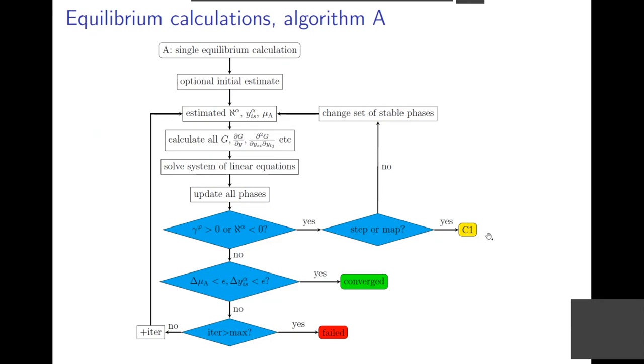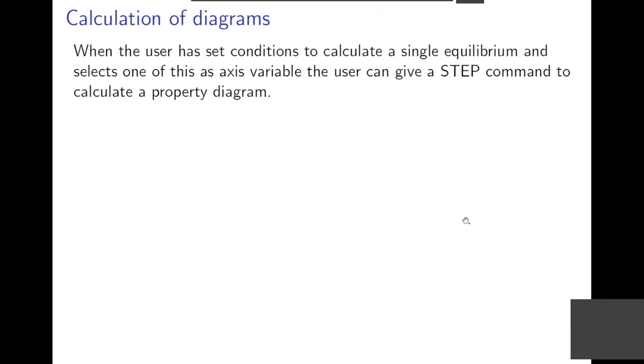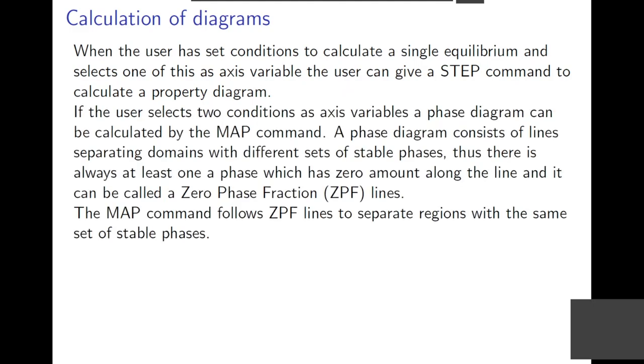If you have a step or map calculation, one goes to a second algorithm here. And there are basically two diagrams you make. One is the phase diagram and one is what we call the property diagram. In the property diagram, you have just one axis and you calculate how the system varies along that axis. The command in OpenCalphad to do a property diagram is a step calculation, and if you want to do a phase diagram, you do a map calculation. And the typical feature of a phase diagram is that it consists of lines separating domains with different sets of stable phases. So there is at least one phase which has zero amount along each line in the phase diagram. John Morral called them zero phase fraction lines. So that's a term we have used in the explanation of this.